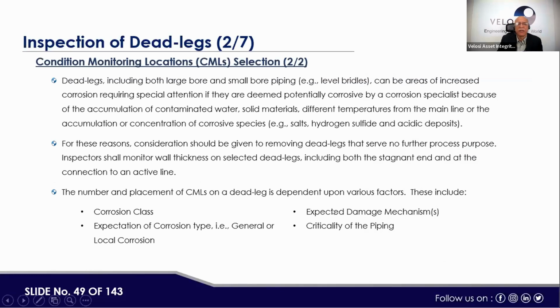Then when we select the CML, TML points, how many points there should be at that particular piping system, we have to take care of the corrosion class, the expectation of the corrosion type, general or localized, expected damage mechanisms, criticality ranking of the piping, and whether there is a potential deposit of corrosion, like at the lower portion or upper portion of the piping system, and whether the pipe is insulated or not insulated. Keeping all these factors in consideration, we try to select the TML, CML locations in accordance with the guideline of API 574.